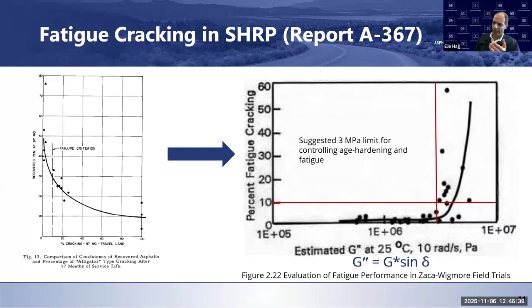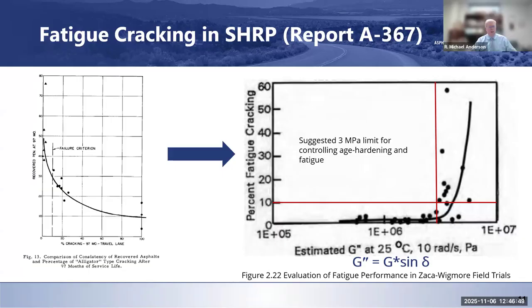Yes, low temperature grade, and in general, if you've observed changes in the binder blending dynamics, and whether that has any influence on the fatigue cracking thresholds. Yeah. So what happens when you're using these materials is you're going to see some blending that goes on for sure. In a lot of cases, there are folks that have suggested that we're using intermediate temperatures that are too warm, maybe, for the climates that we've got.